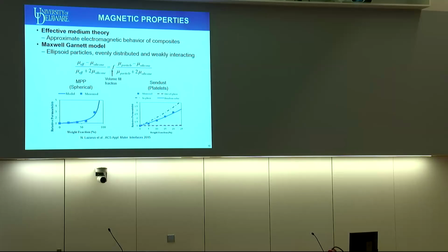In this particular situation, the appropriate model is something called the Maxwell-Garnett model. And we found that our behavior matched the expected behavior very closely, both for the more spherical particulate, the permalloy powder, as well as for the more platelet geometry. We found that it matched what you would expect for a fairly random orientation of these platelet materials, as we'd expect from randomly stirring it into the material.